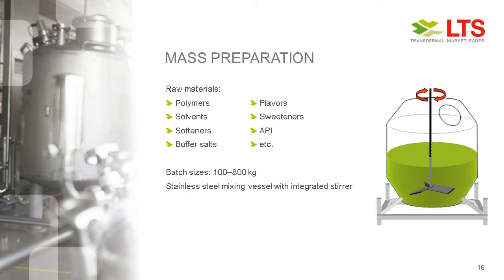So the first step is the mass preparation, and as you can see here, it shows schematically just a mixing vessel of a certain size, a few hundred or up to 1,000 liters, and it can be as easy as it looks here: you simply mix all raw materials like polymers, flavors, sweeteners with the solvent together, and you add softeners, buffer salts, plus the API into this mixing and create a homogeneous solution out of it. But, of course, the reality never looks as easy as this. Very often we need additional steps like a high-speed homogenizer or certain temperature profiles to get everything dissolved or dispersed in the way that we need it for the next step. And usually batch sizes which are used on a commercial scale are in the range of 100 to 800 kilograms. This can differ sometimes depending on the product volume, of course, but this is the standard range.